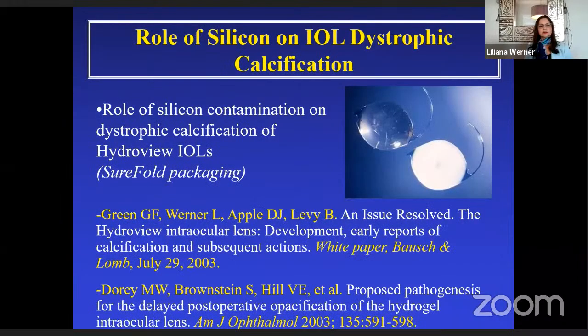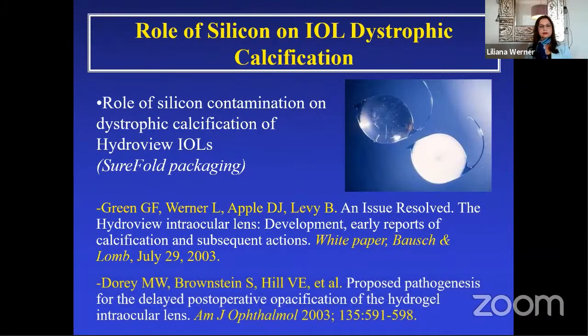In the case of the HydroView lens from Bausch & Lomb, some studies indicated that the problem of postoperative calcification was related to a change in the lens packaging. The new package contained components made of silicon. It is suggested by different studies that the element silicon is associated with calcium in an early stage of calcification.